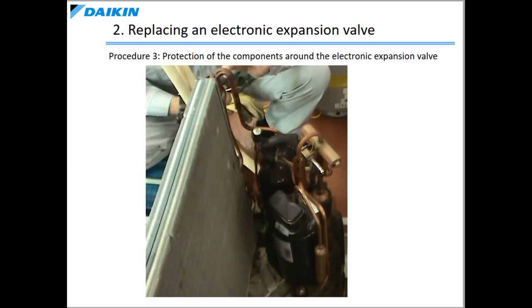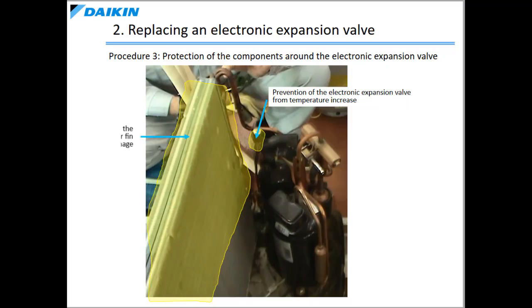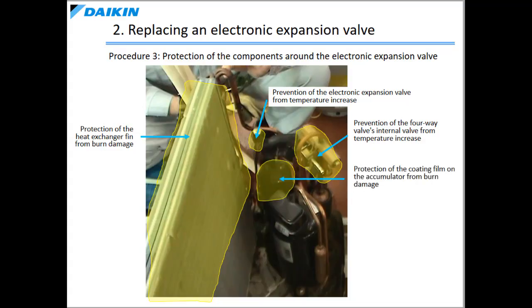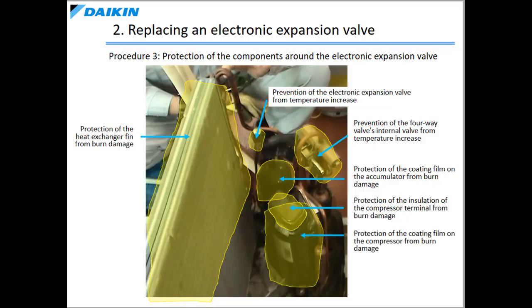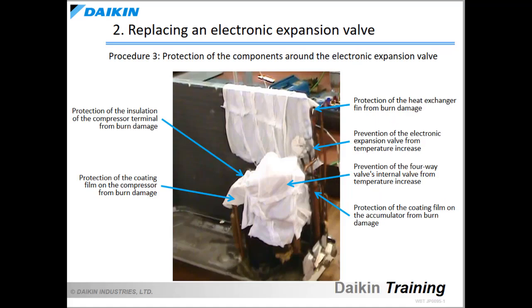After the protection of the electronic expansion valve main body has been completed, protect all the components around it. Protection of the components around the electronic expansion valve includes prevention of the electronic expansion valve from temperature increase, protection of the heat exchanger fin from burn damage, prevention of the four-way valve's internal valve from temperature increase, protection of the coating film on the accumulator from burn damage, protection of the insulation of the compressor terminal from burn damage, and protection of the coating film on the compressor from burn damage. As shown in the photo, protect those components so that they will not be damaged by coming into direct contact with the flame. The actual protection is as shown in the photo.